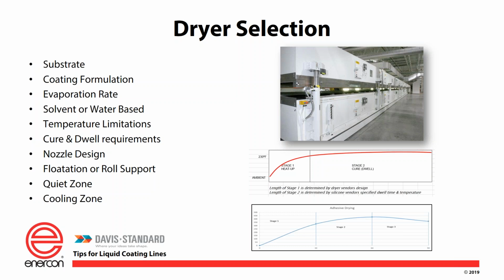On a recirculation, what you're going to do is heat up air, apply it to the substrate, and create a gaseous form, which then goes out through your exhaust. To cut your costs down, you don't want to have to heat virgin air all the time, so you can recirc some of that heated air back in. The more water you have in that air, the less efficient your drying is going to be. So in zone 1, maybe a low recirculation number would be used, whereas in zones 2 and 3, I can increase the amount that I'm recirculating and cut down my operating cost.